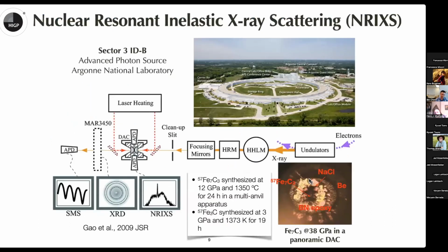So we utilize the technique called nuclear resonant inelastic X-ray scattering, NRIXS, available at sector 3 of the Advanced Photon Source. In this experimental beamline, X-ray diffraction and synchrotron Mössbauer techniques are also available. We loaded our samples, synthesized in a multi-anvil press, iron-57 enriched Fe7C3 and Fe3C, in a diamond anvil cell called the panoramic diamond anvil cell with 150 micron culet diamond. We compressed the samples at room temperature up to 1.5 megabar, and then we collected the NRIXS data for the samples.